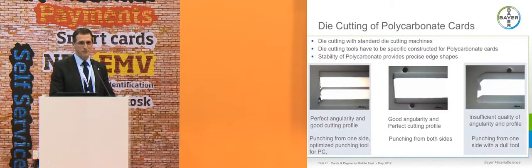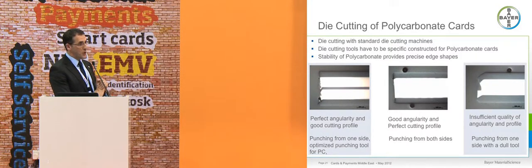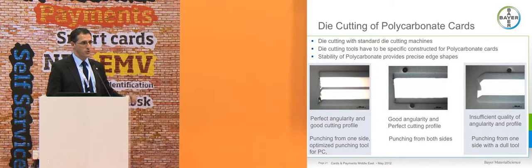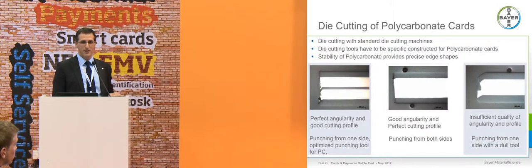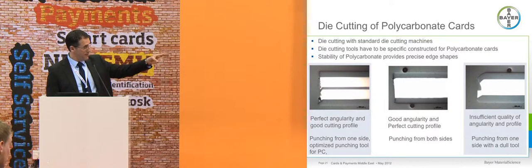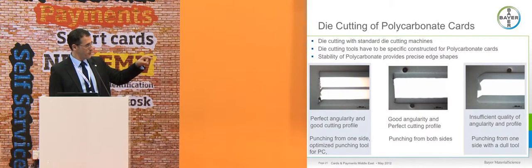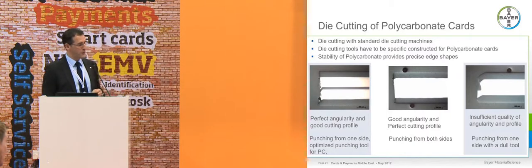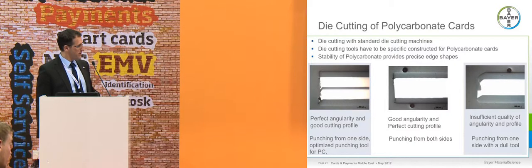Die cutting, this is something you have to pay attention to when you work with polycarbonate films. For die cutting or punching polycarbonate films, special tools are required, tools which are compatible with polycarbonate, because by using PVC tools to punch polycarbonate cards, you will find yourself in trouble. A die cutting or punching tool for PVC will very soon give up the operation, and the edge quality will not be fine enough. As you can see in these pictures, on the very right side the edge quality of this card is quite bad. Yes, done with an appropriate tool for polycarbonate. Here on the very left side, you see the edge quality is very good.